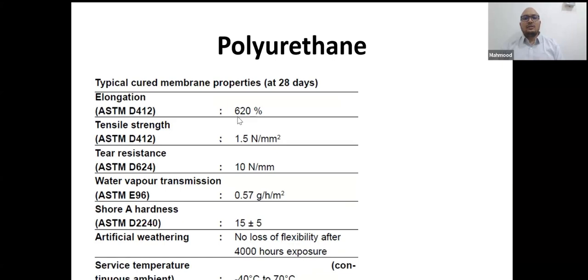See, the elongation is 620% and tensile strength is 1.5 Newton per millimeter square and tear resistance 10 Newton per mm and water vapor transmission. And you can see the service temperature -40 to 70 degrees Celsius.